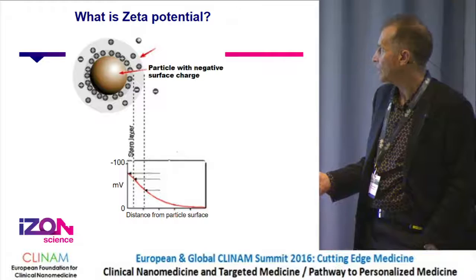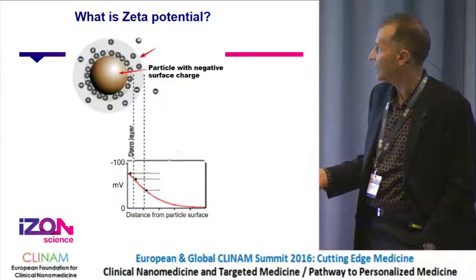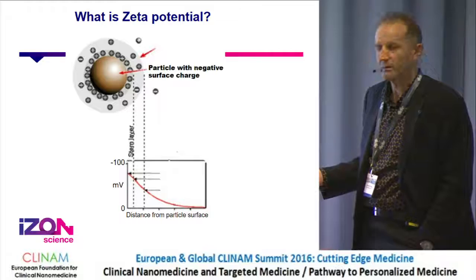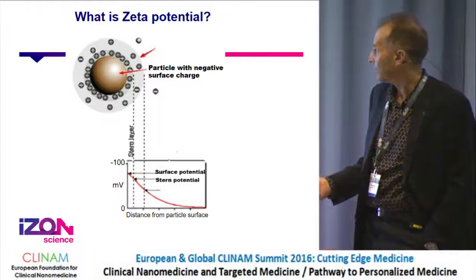What is zeta potential? You've got this Stern layer, so it's the voltage at the slip plane — that's the definition. But of course you've got this artificial round ball — a little bit of gold or a ball-looking thing. When you move into nano-bioconstructs, you don't have that anymore. So that concept, in my opinion, ceases to have too much relevance, but we keep using it because everybody insists on it. There's a real limitation to being stuck with that simplified model.